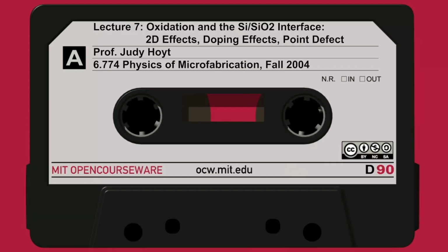It might even affect the solubility. You might imagine, hypothetically, that the amount of water vapor molecules or oxygen you can stuff in there would be affected by how much pressure this solid is under. So again, mathematically, we can do what we did before. We write the stressed diffusivity as the normal planar diffusivity through the oxide, times something that depends exponentially on the pressure, which is the hydrostatic pressure due to the oxide stress, times a constant, which is a fitting parameter, Vd, over kT. So again, D will go down as you go under stress, and you might hypothesize the same thing for the solubility, a similar dependence.